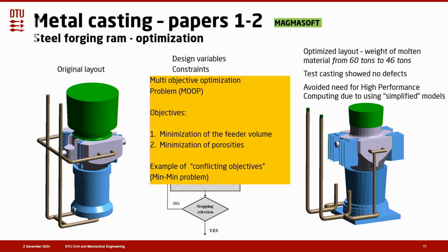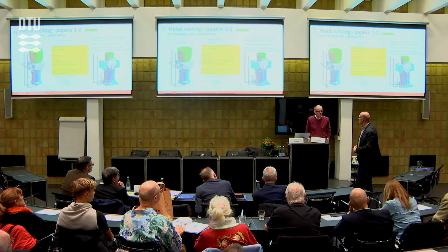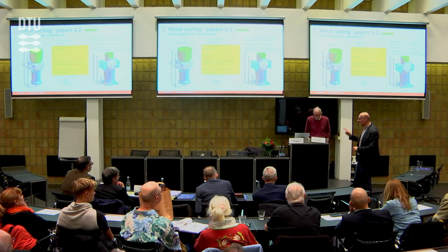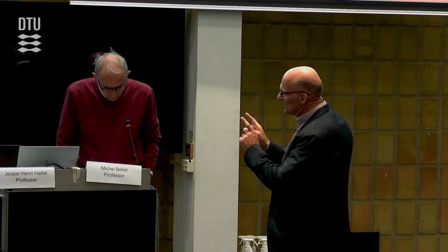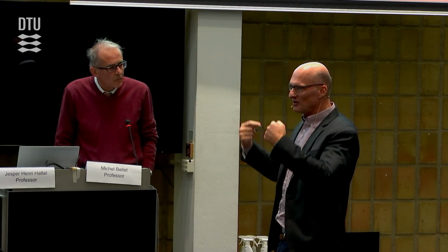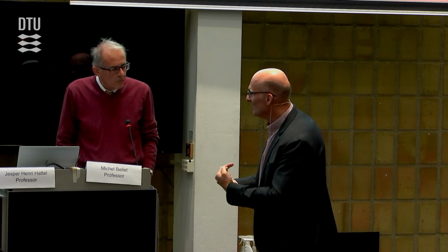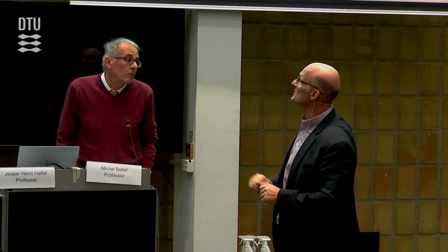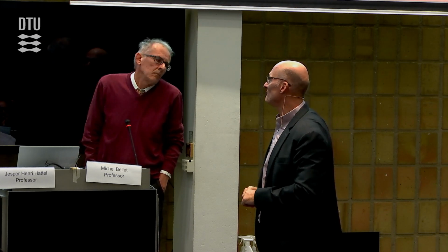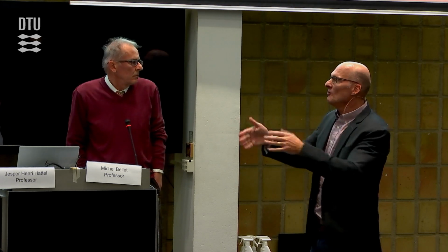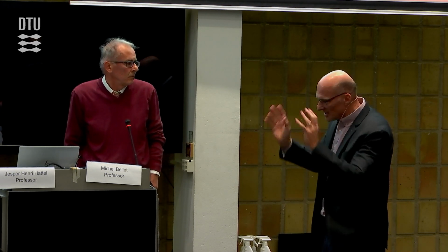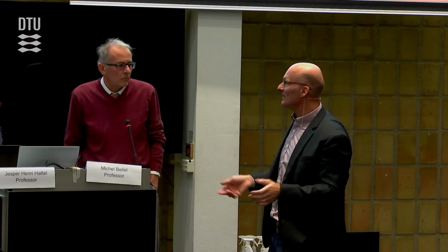And it was cast by Vítkovice Heavy Machinery, a humongously big plant in the Czech Republic, and it showed no defects. That was really interesting. Then we took Magmasoft afterwards and did the fluid flow simulation again to check the one that was optimized only based on the thermal field, and we saw that we got a lot less centerline porosities as well as segregation.